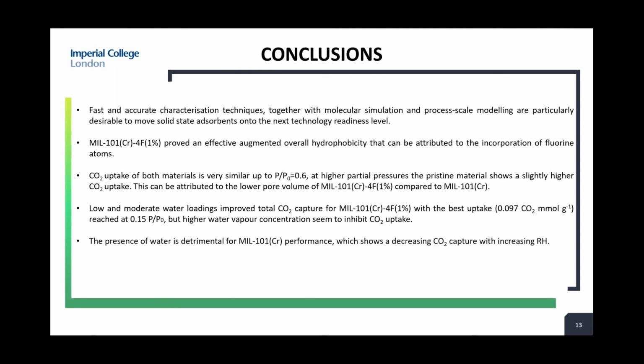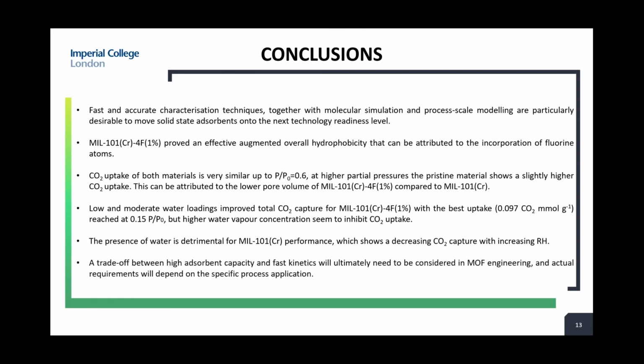So the presence of water is detrimental for the non-modified MIL-101 performance, which shows a decreasing CO2 capture with increasing relative humidity or partial pressure, and ultimately a trade-off between high adsorbent capacity and fast kinetics needs to be considered in MOF engineering, and actual requirements will depend on the specific process application.